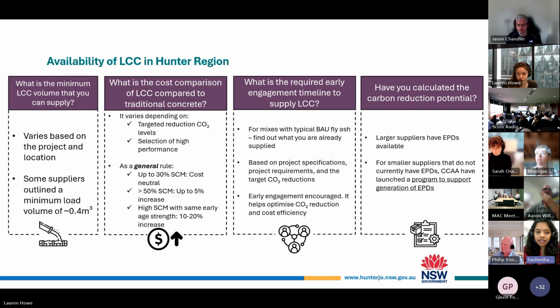So as a general rule, based on our experience working in this space across the country, up to 30% of SCM replacement will be cost neutral. But if you replace more than 50% of SCM without having the comparable early age strength to traditional concrete, the cost increase will be up to 5%. And if you have high SCMs with the same early age strength compared to traditional concrete, your cost increase will be 10 to 20%.